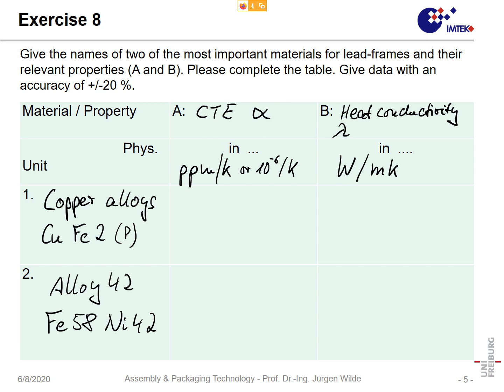Now, what is the advantage of copper alloys? The advantage of copper alloys is that it preserves the high thermal conductivity of pure copper. So typically it's roughly 260 watt per meter Kelvin. That's a very high value. Pure copper has roughly 400. Alloying always degrades conductivity. That's both in thermal conductivity and in electrical conductivity.